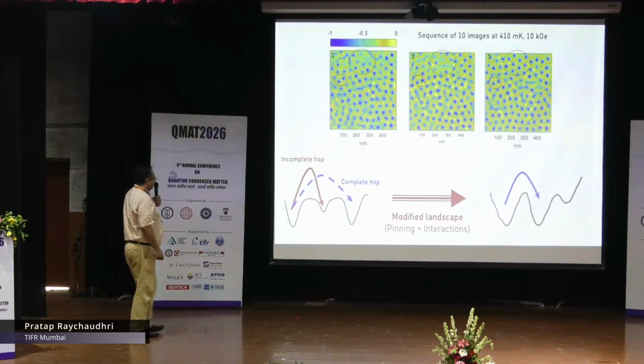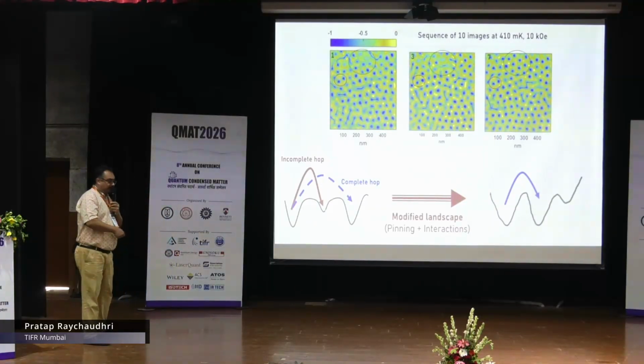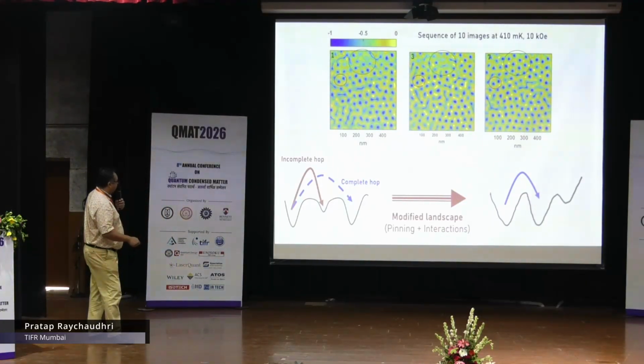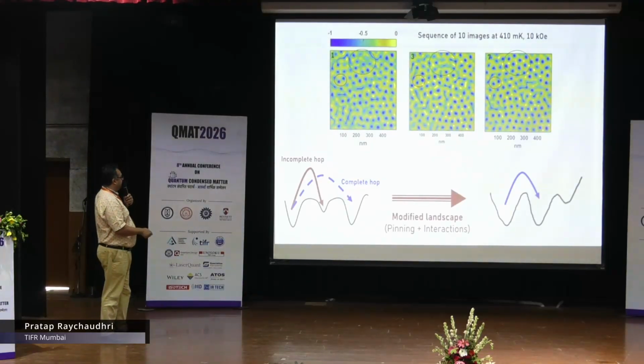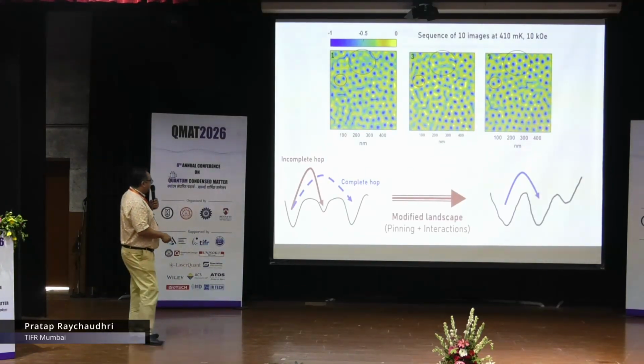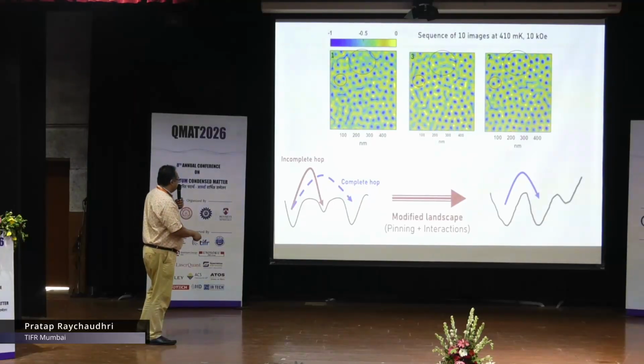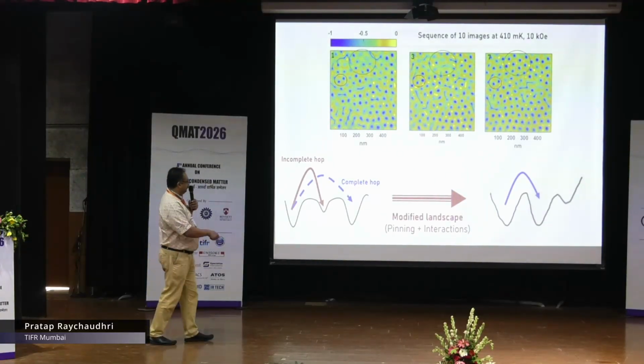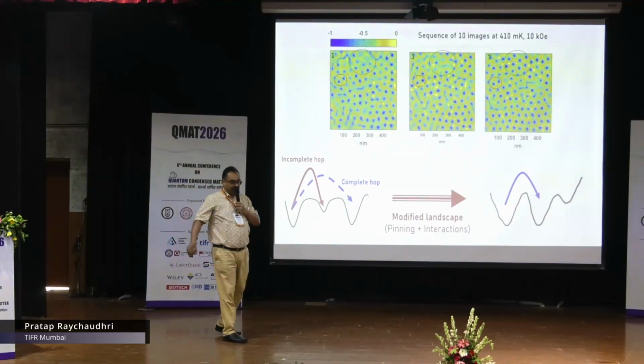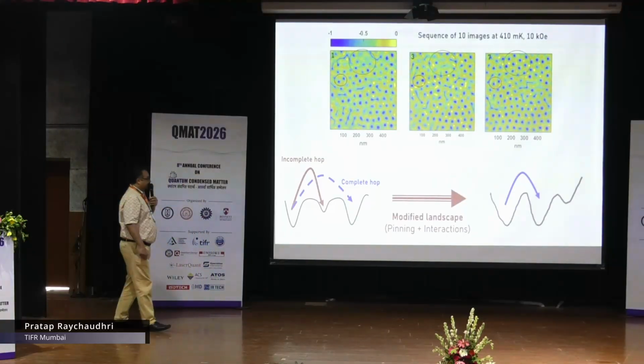This happens because of this. What I showed you earlier was what I call a complete hop. The vortex is jumping from one minima to the next minima, but every once in a while, it can also get trapped into an intermediate minima, which I call an incomplete hop. And then when it gets trapped here, in the next image this small minima will become the dominant minima, and this dominant minima will become the subdominant minima.